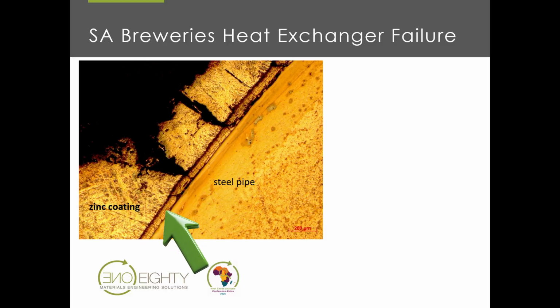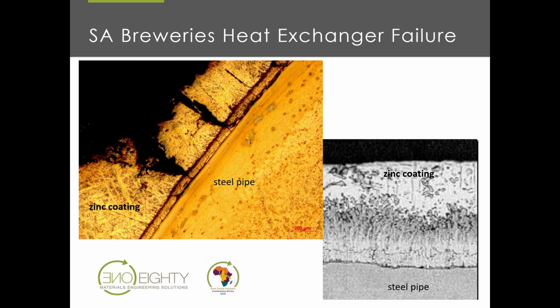and the zinc coating. I'm sure you can see that there's a lot wrong with that, right? We agree that there's a lot wrong with that zinc coating. Okay, first of all, it's cracked. The layers have not formed in a homogeneous manner. And it gets worse. If you look over here, it appears as though we have the same problem as the paint coating, where there is rust underneath the galvanizing.